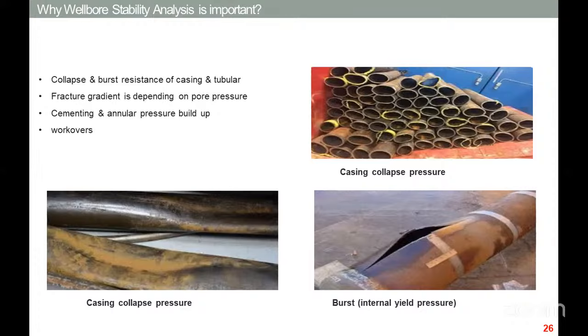Also, if you're drilling in the Gulf of Suez, we have an active salt. For this salt, you need a higher casing grade, because if you're using a low grade, the salt is movable, especially in the southern part of the Gulf. In this case the salt moves and the casing collapses, and we have many cases dealing with this. You use a low grade, didn't estimate that the salt moves and the stress is very high. You should use a casing with a high grade. It's more expensive, but it's safer than losing the well.